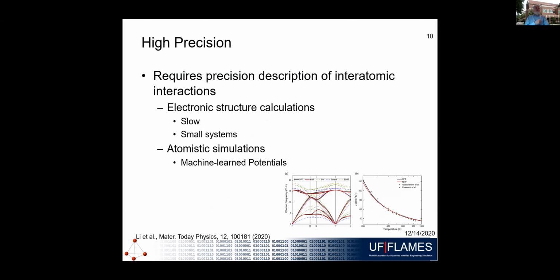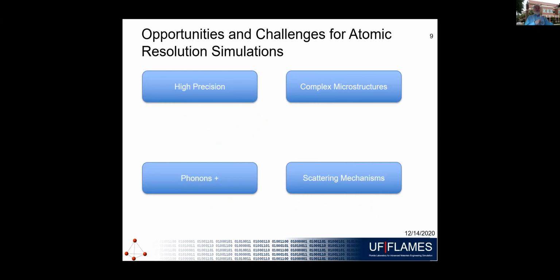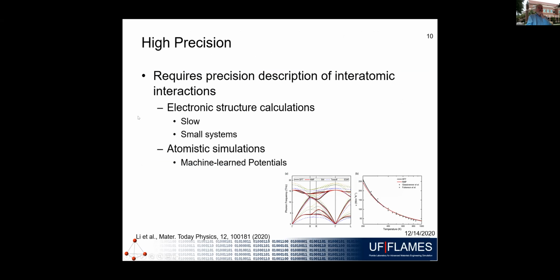So the opportunities I see are increasing the precision of calculations, looking at complex microstructure, what I call phonons plus, which is adding other excitations to the phonons, and getting more information about scattering mechanisms. So this was covered by Professor Snyder, and one of the other talks mentioned this, which is increasing the precision of interatomic interactions. And so I think the frontier here is using AI for machine learned potentials. So taking electronic structure calculations, which are slow, taking the results from those to develop machine learned potentials.